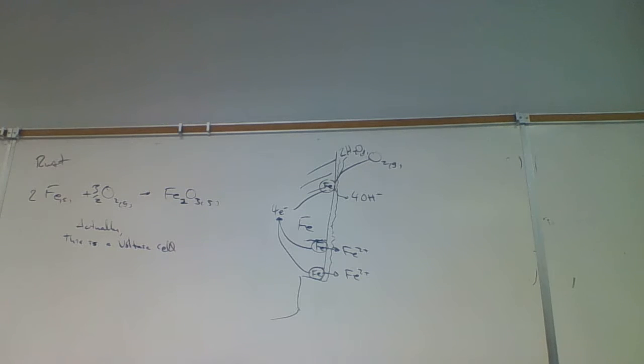And so here's a little diagram here. Here's our cathode. The oxygen and the water come along, forming the hydroxide. Hydroxide turns to rust. And so here's the iron, and we just need zinc attached to this. If there's any zinc attached to this, then the zinc, having a higher oxidation potential, will be oxidized. The zinc has to be in electrical contact with the iron, so the electrons can travel. So here we're going to have corrosion of zinc instead of the iron. And that works until all the zinc is eaten away. Once all the zinc is eaten away, then the nails will start to corrode.